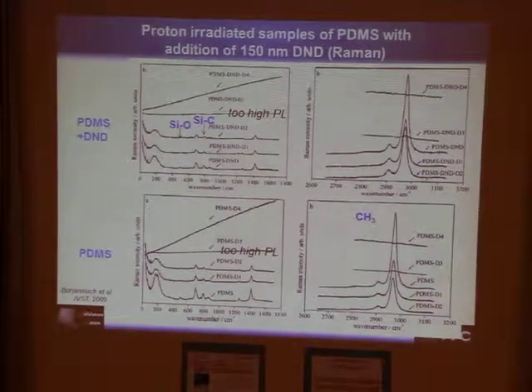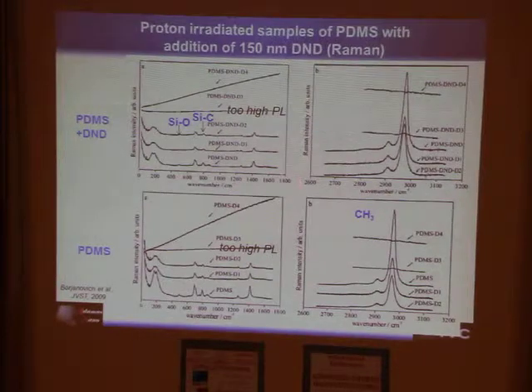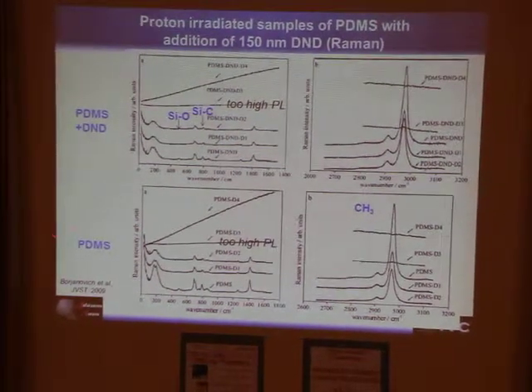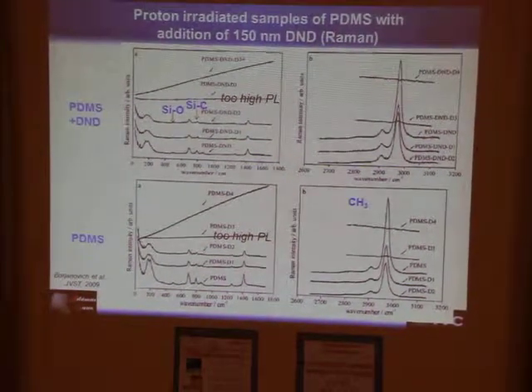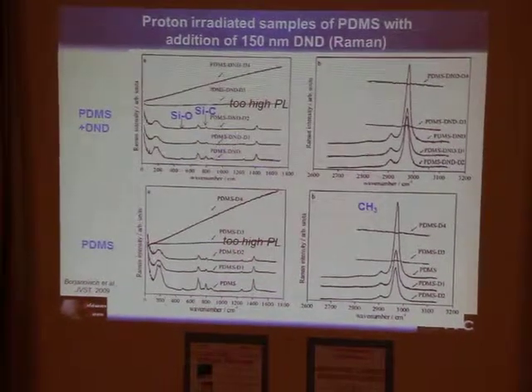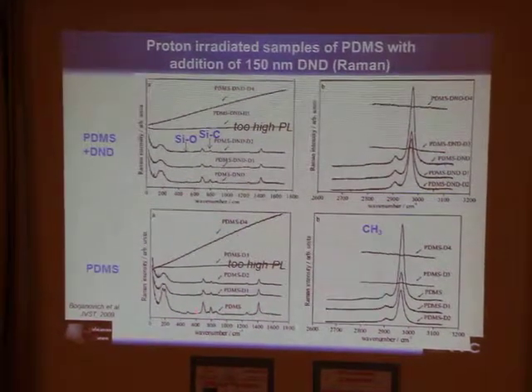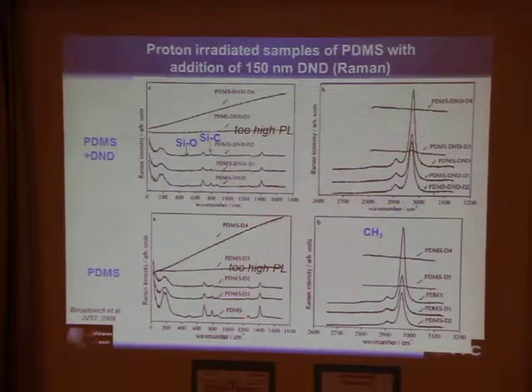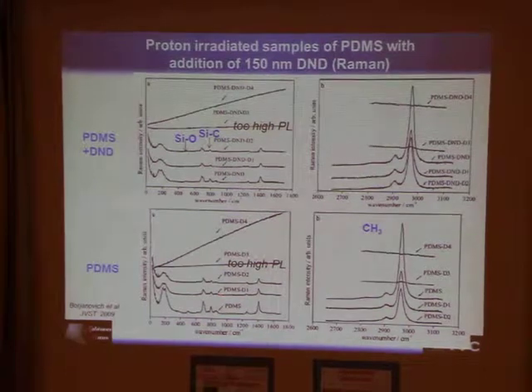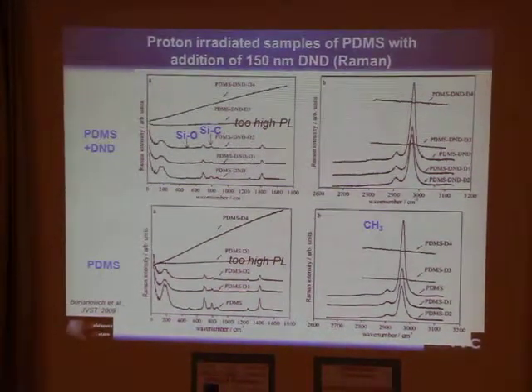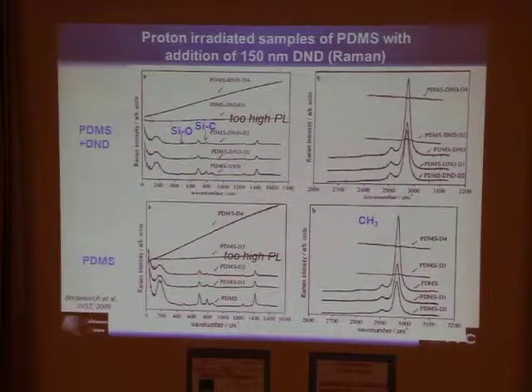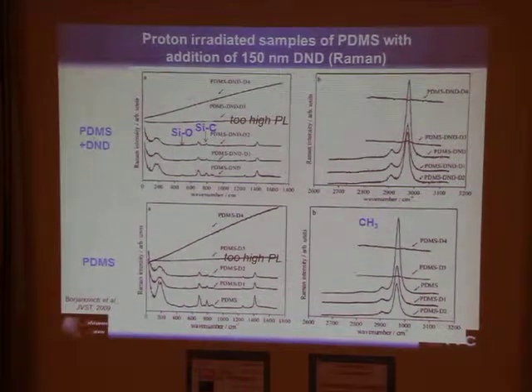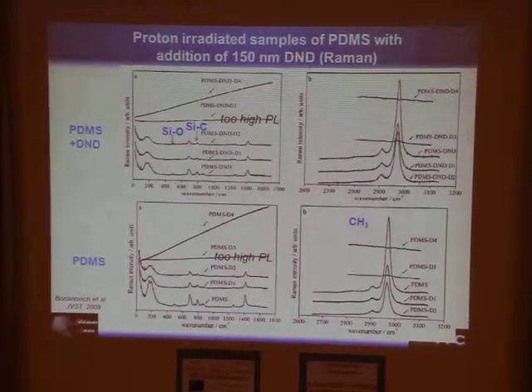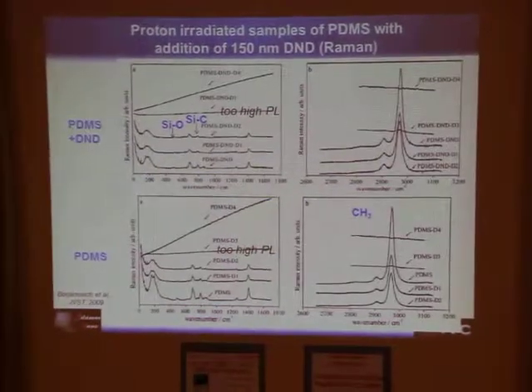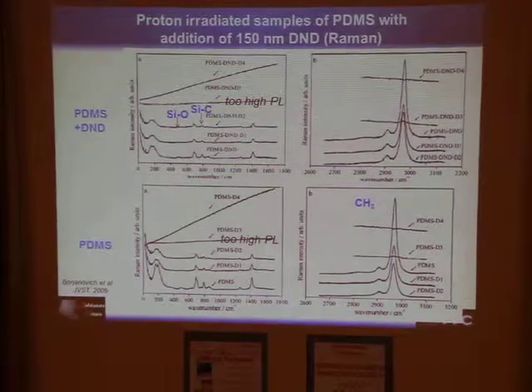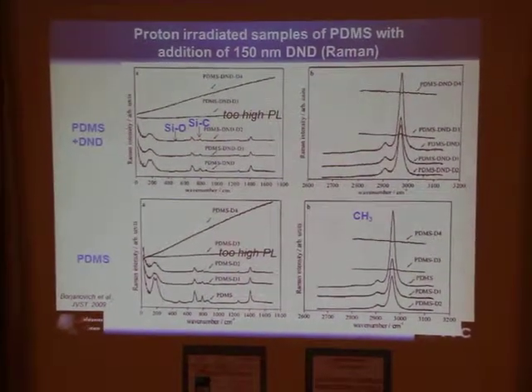This is again Raman spectra for 150 nanometer nanodiamond composites and for pure PDMS irradiated at those 4 doses that I provided before. What you can see is that this is the spectra for pure PDMS. This is for D1, dose 1. You can see that some characteristic peaks' intensity started to decrease. At dose 2, which is the same dose but higher current, you can see that peaks became even less pronounced. However, photoluminescence was too high for the highest irradiation dose, so it was not possible to do structural analysis of Raman spectra.